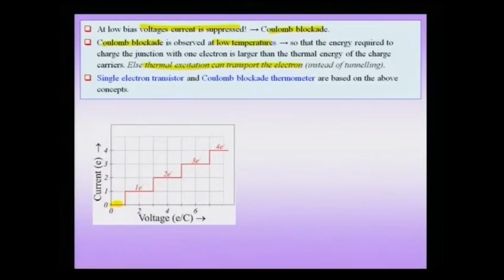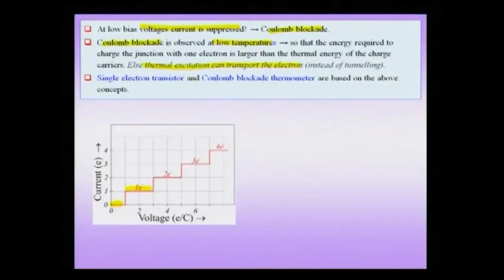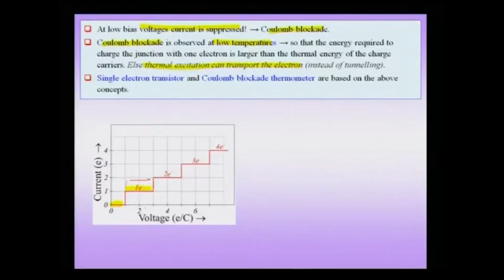So, what is the essence of this Coulomb blockade phenomenon? Initially, of course, at low voltages there is no current at all, and when you apply sufficient voltage, the system charges to one electron. But in this regime, from here to here, further increase in voltage does not lead to an increase in current, because the pre-existing charge in the capacitor effectively stops a second electron from entering the capacitive system. That implies I have to again break down this capacitor, for which I have to employ a higher voltage, and once I have charged the system with 2 electrons, again you find a plateau in the current-voltage characteristics.